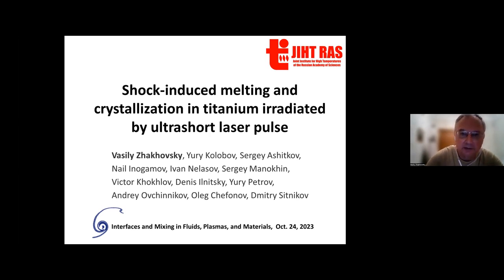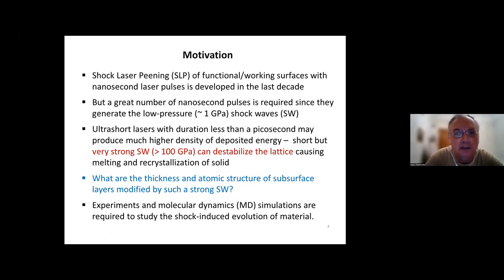Okay, next. Recently, in the past decade, shock laser peening technology, a kind of new technology using nanosecond laser pulses, was developed. It is very useful for improving the mechanical properties of the working surface of tools or materials. However, this technology uses a great number of nanosecond pulses, and each pulse has quite low energy and generates a low pressure shock wave with pressure about 1 GPa.